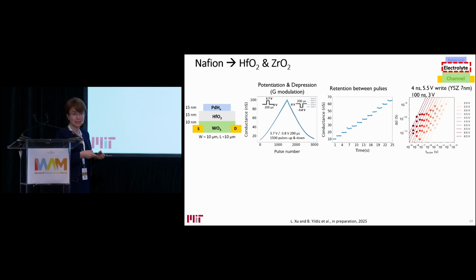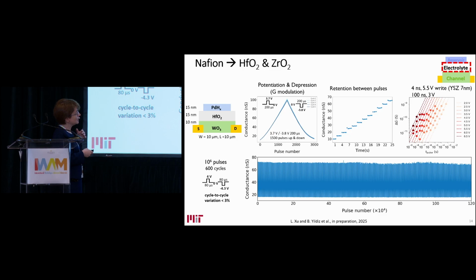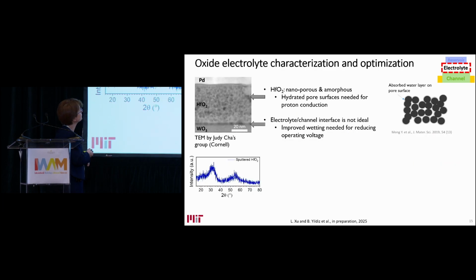So silica is not the only inorganic system that we can work with. We have also demonstrated very good behavior with thin film hafnia and zirconia, where again we get potentiation and depression by sending protons in, extracting them out. There is good retention between pulses, and again, strongly nonlinear dependence on the voltage that we apply. And as I said at the beginning, these are not filamentary devices. We are dealing with ion intercalation. Therefore, the repeatability of the behavior cycle to cycle and also device to device, which I'm not showing here, but you can ask me if you like later, is really good and already meets the targets for hardware DNN applications.